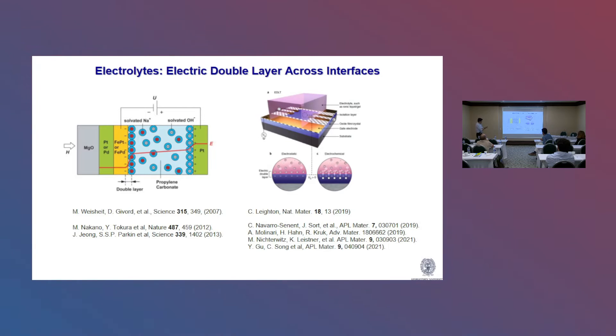The magnetic version can be traced to the seminal work by Dominique Givord's group that uses electrolyte to gate. Under this electric field, there's charge accumulation on the exterior surface of the material, which induces electrostatically another layer of the opposite charge. So you have this electric double layer near the surface. And this modifies the carrier concentration and the material properties, such as anisotropy. And there has been a number of excellent review articles here.